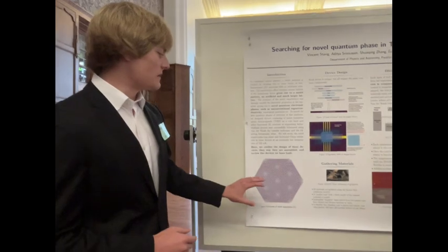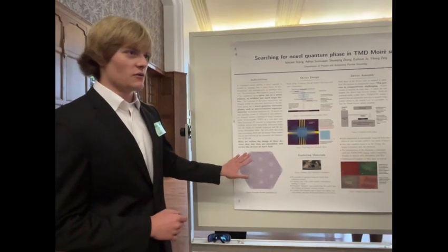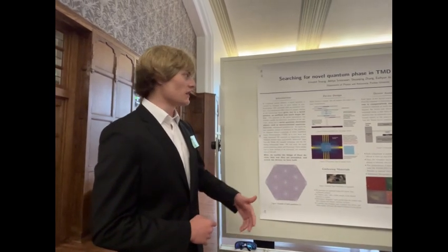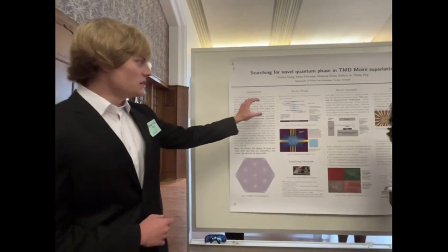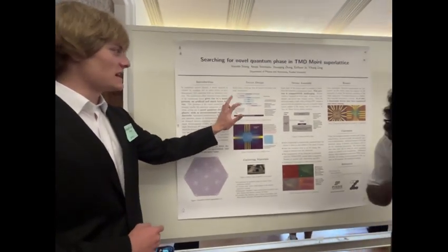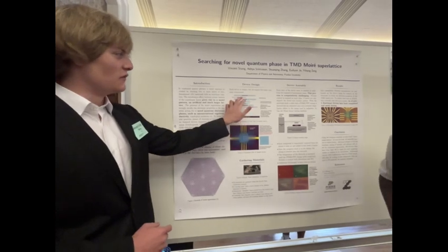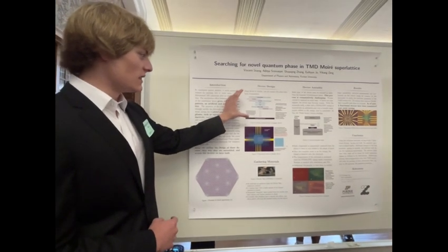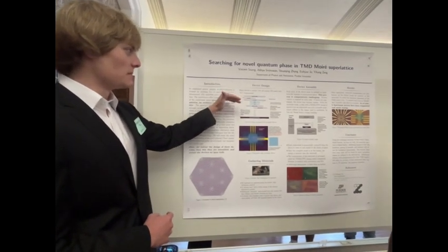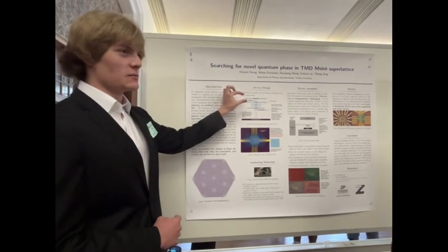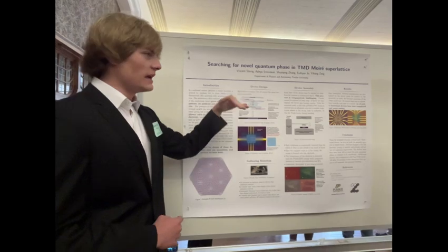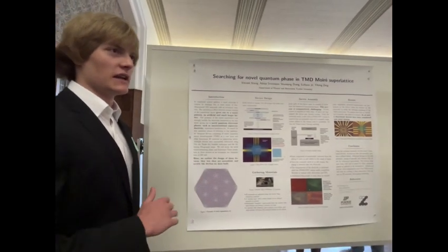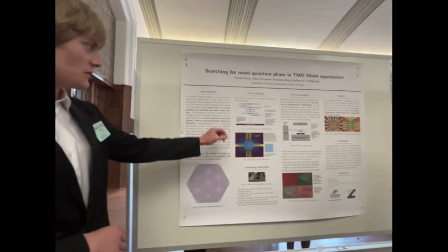And what we do in our lab is instead of assembling these superlattices from graphene, we use TMD, which is transition metal dichalcogenide. This is another class of material. So we stack them into these devices to test the electronic properties, or basically put a voltage over TMD Moiré superlattices. So this is a sample design. I'll go through each layer from top to bottom, but for reference, no layer is more than maybe 3 atoms thick, and then in the plane of the material, they're not longer or wider than maybe 80 micron. So it's about the scale of a human hair if you look down a microscope.